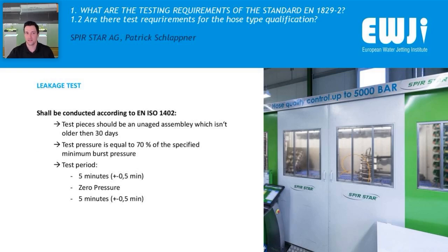What is a leakage test? A leakage test shall be conducted according to EN ISO 1402. Here, the test piece should be an unaged assembly, which isn't older than 30 days. The test pressure is equal to 70% of the specified minimum burst pressure. Here, we test the hose for 5 minutes, then we reduce the pressure to 0, and then we test the hose for 5 minutes again. If there's no leakage, the hose passed the test.